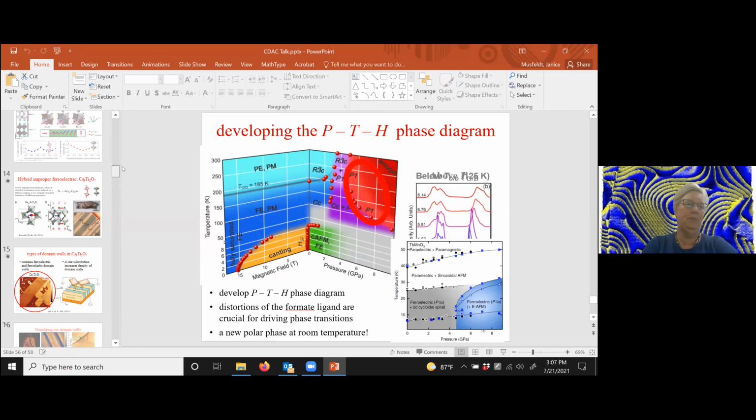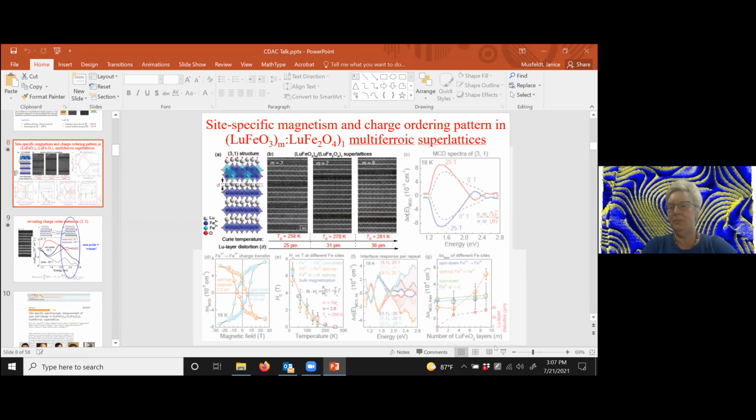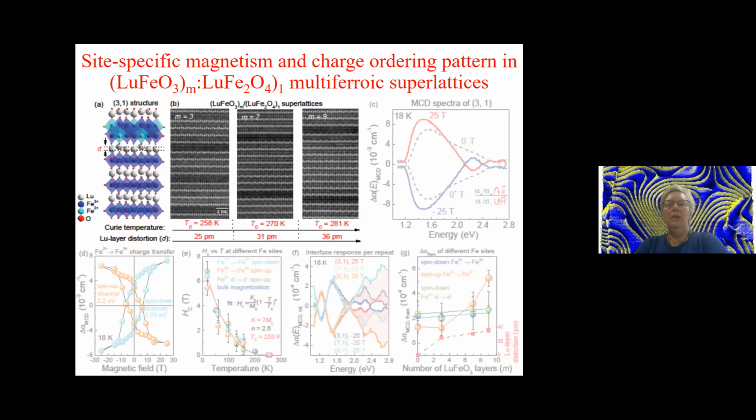Let's see. It's this. Okay. So one of the things we always do when measuring a multiferroic is that we do a training loop because there might be some hysteresis in the material. And you'll notice that what we have here is a 0 plus and a 0 minus. That just means we're sweeping up or sweeping down. So in other words, the zeros aren't the same.